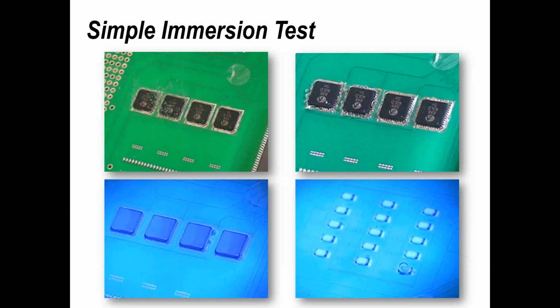And if you look closely, and I've taken just 4 still images here, you can see the reaction, the gassing which is taking place because of the chemical reaction between the applied voltage across the gap and the distilled water, which is in this particular sample. That's top left. Top right, you can see the bubble formation, which is the gaseous reaction. And the 2 examples underneath are literally where we've got a board which had conformal coating on. It wasn't coating properly, both the surface of some of the chip components, which you see on bottom right, and certainly it wasn't protecting all the way around the QFN LGAs.